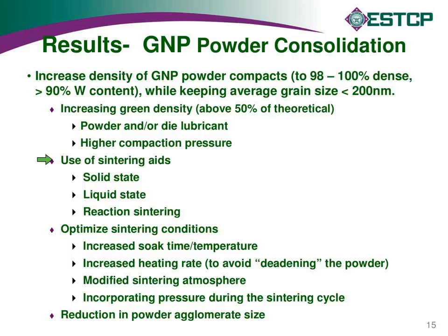And then we tried a series of things in sintering conditions, whether it was soak times, heating rates, or modified sintering atmospheres, so that we could control the sintering, because it's a diffusion controlled process, and there's even some vapor involved in that. And then what we found was that during the sintering processes, we just could not get it to the high densities without pressure, and we tried a variety of sintering aids. So then we decided the only approach was to incorporate pressure during our sintering cycle. So this is more like a hot pressing operation or a hot isostatic pressing, and these were things that we did.